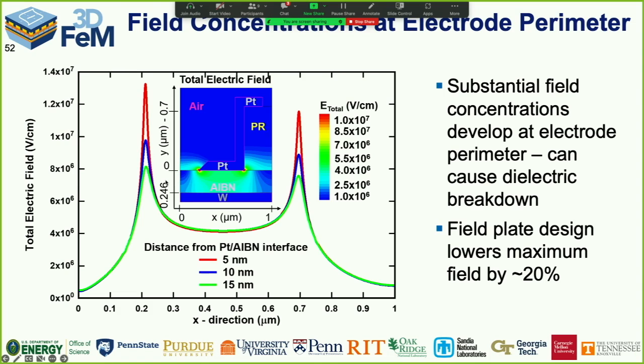And not surprisingly, at electrode discontinuities, you end up with huge field concentrations. So even though these materials have big breakdown strengths, if you apply electric fields that are many times the coercive field at the electrode perimeter, you're very likely to blow the material up. And so what we're learning how to do is to design field plates. You'll notice the same material, same electric field. We can drop the maximum field if we're a little more clever about the design than the average material scientist.